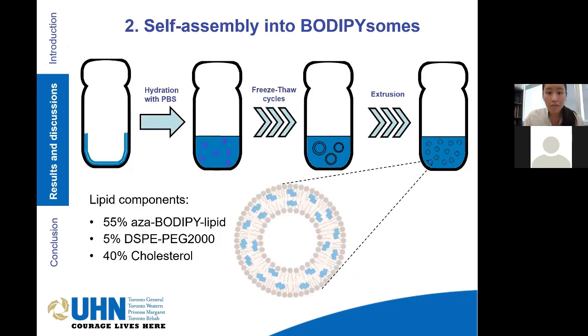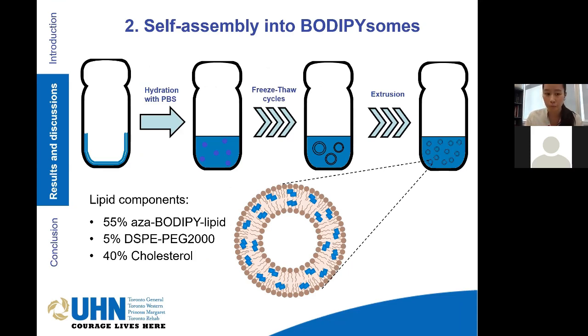Through using the freeze-thaw extrusion method, I was able to screen different formulations of these BODIPYsomes and ultimately optimize a formulation that only requires three components: the aza-BODIPY lipid, DSPE-PEG2000, and cholesterol.